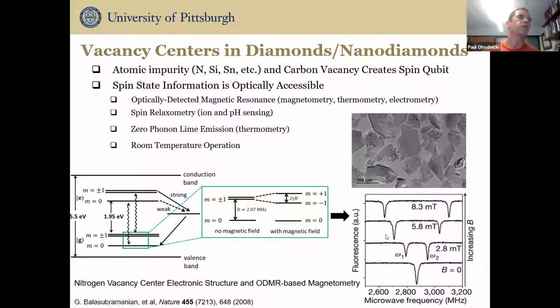And while we're measuring fluorescence, we can also apply a microwave of characteristic frequency. And as we sweep the microwave, you see that we get characteristic resonance peaks in the fluorescence, which are related to the splitting due to the application of an applied magnetic field. And so this can be very effective at sensing very low-level magnetic fields.